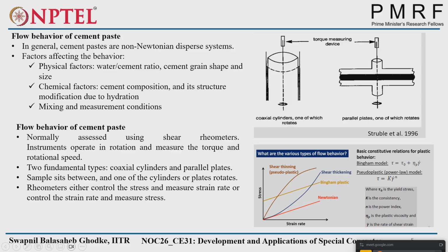So the Bingham model: you see tau is equal to tau zero plus eta p gamma dot. This intercept is called tau zero, the initial yield stress. Eta p is the plastic viscosity, which is the slope of this Bingham plastic graph, and gamma dot is the shear rate.